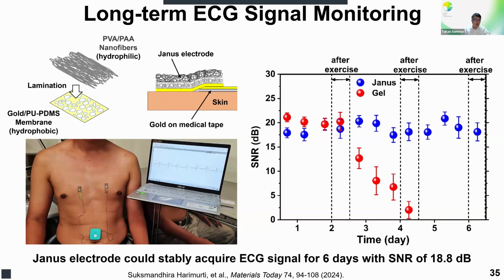And recently, we improved the durability of nanomesh. Simultaneously, we developed the Janus membrane that works as a pump to remove the penetrating sweat immediately. Our Janus membrane-based skin electrode exhibits amazing stability, and we succeeded in monitoring the ECG signal continuously over 6 days without degrading the signal to noise ratio.